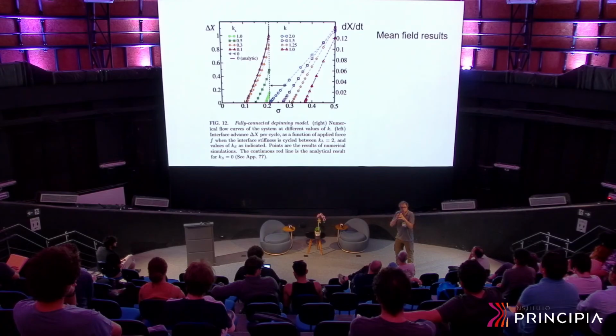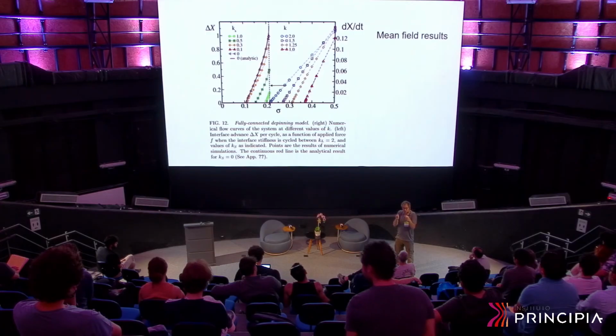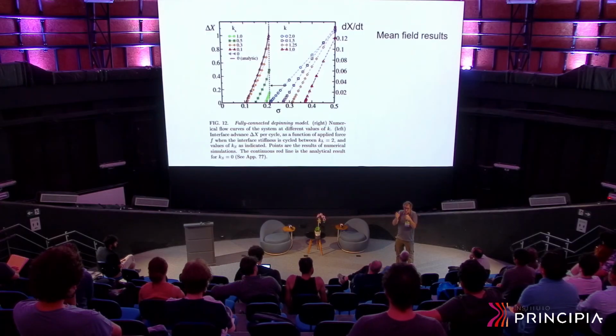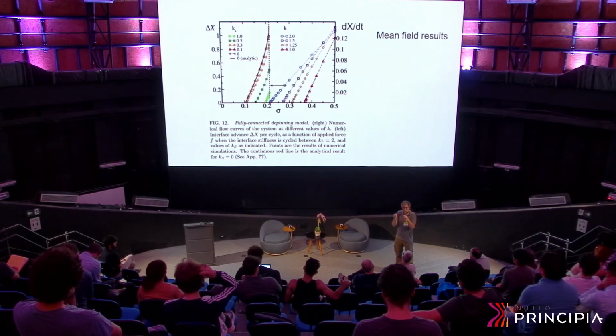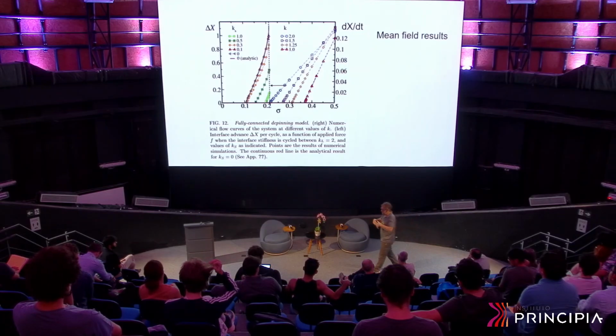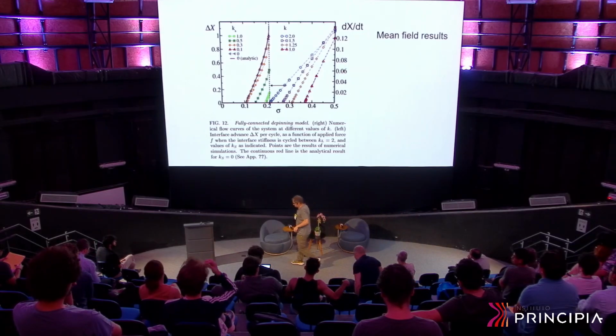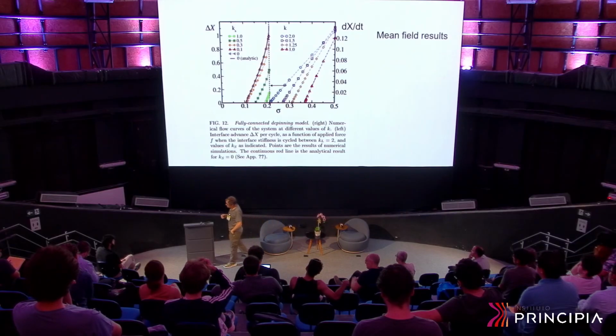If you have a metallic piece of material or something like that with some pre-existing crack, and you apply a stress onto the material, of course, if you apply a very large stress, you will break the material. But if you apply a stress that is small, typically the system is stable. But if you start to increase the stress and decrease the stress, even keeping all the stresses below the critical stress for running out of the crack, this oscillation of the stress produces an increase in the length of the crack a small amount every cycle. This is a well-known phenomenon.